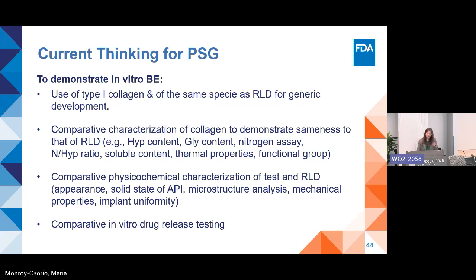So based on our research findings, we have several recommendations, which reflect our current thinking for the PSG development. Our first recommendation is use of type 1 collagen from the same species as RLD for the generic development. Additionally, a comparative characterization method should be established to demonstrate sameness of the collagen to that of RLD. For example, hydroxyproline content, glycine content, nitrogen assay, nitrogen over hydroxyproline ratio, soluble collagen content. All of these parameters can be used to demonstrate the sameness of the collagen compared to the RLD. Of course, comparative physicochemical characterization of the test and RLD, including comparative in vitro release study, should be provided to provide the equivalence of product performance between test and RLD.